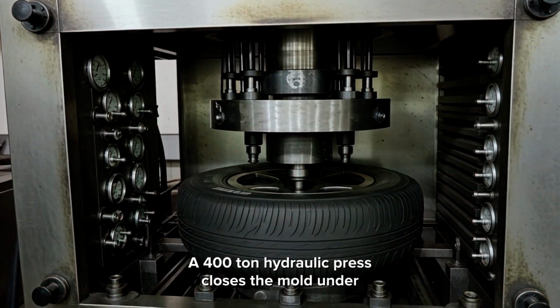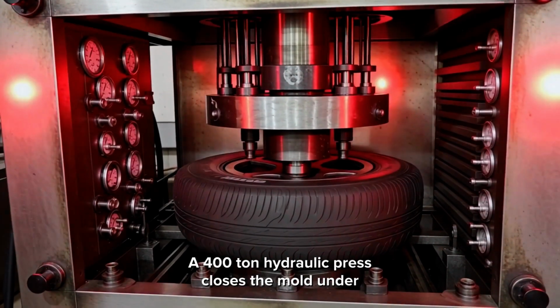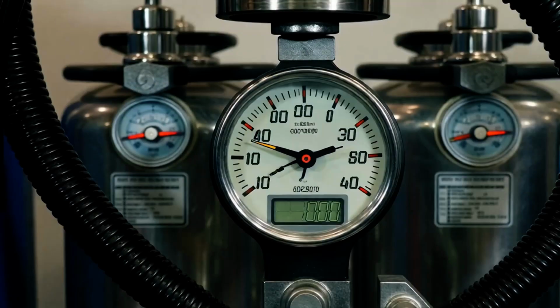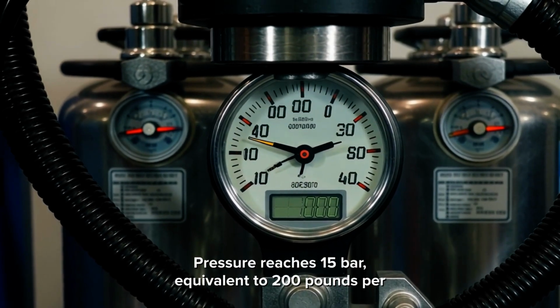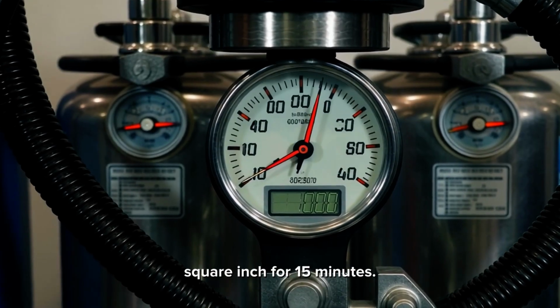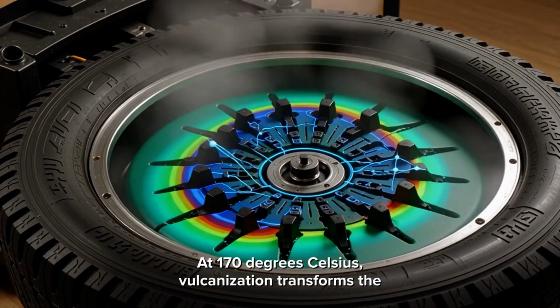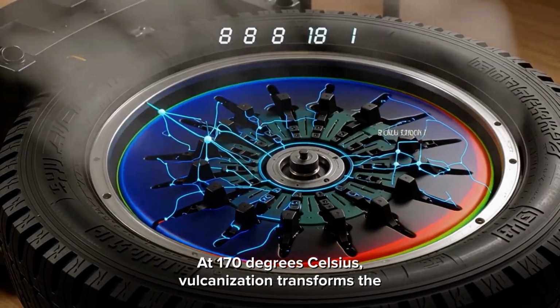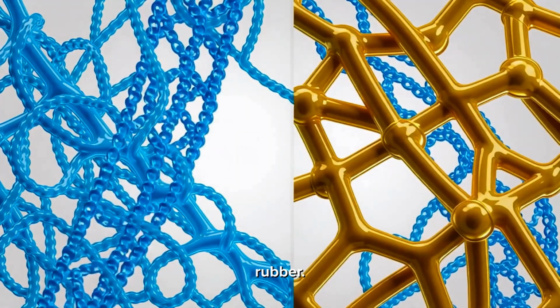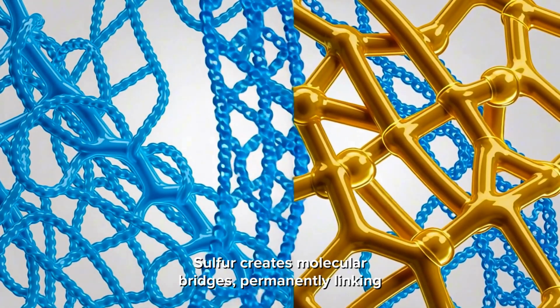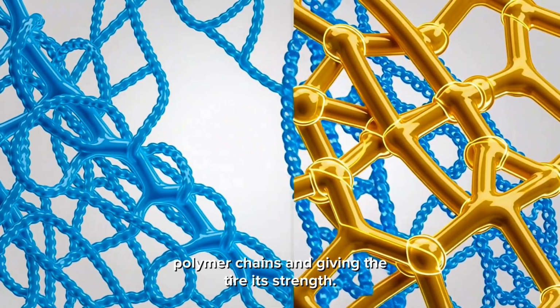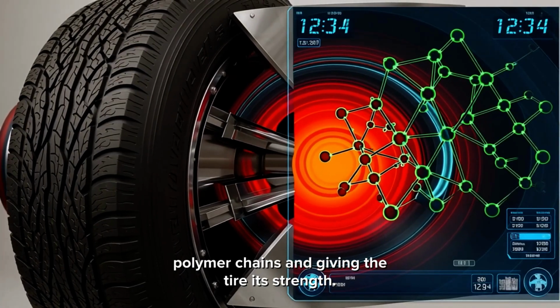A 400-ton hydraulic press closes the mold under enormous force. Pressure reaches 15 bar, equivalent to 200 pounds per square inch. For 15 minutes at 170 degrees Celsius, vulcanization transforms the rubber. Sulfur creates molecular bridges, permanently linking polymer chains and giving the tire its strength.